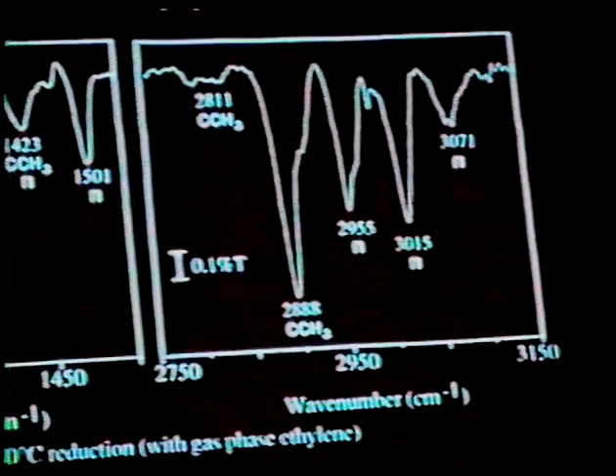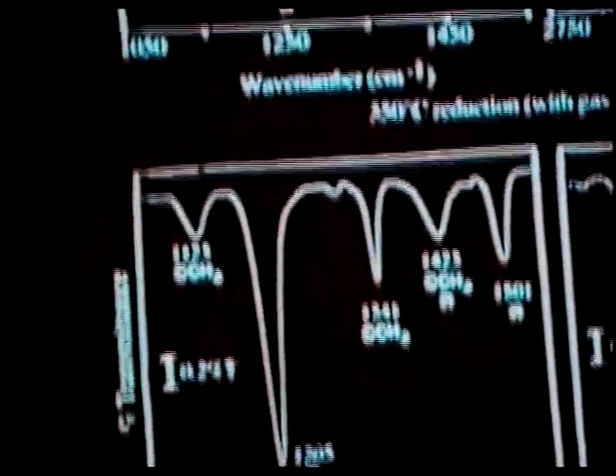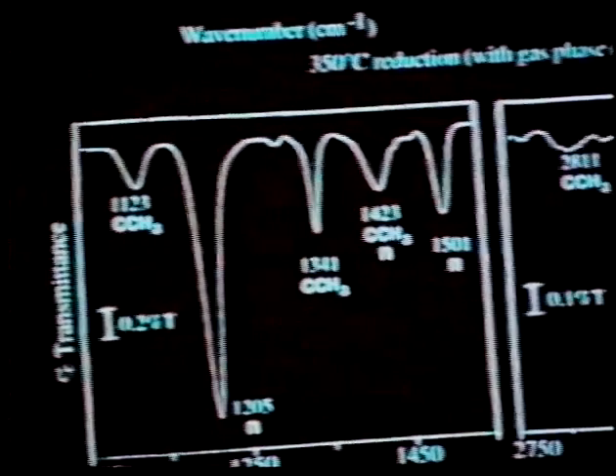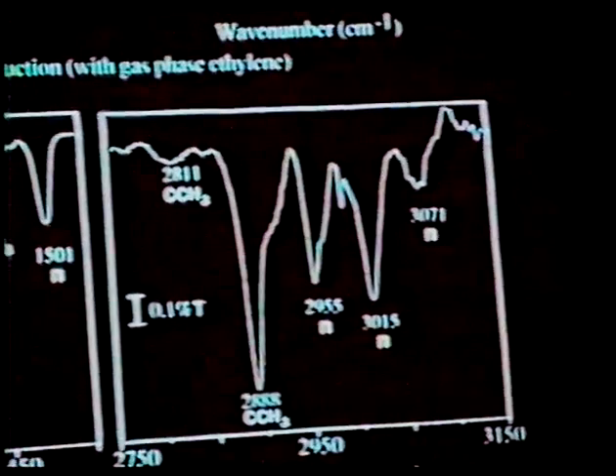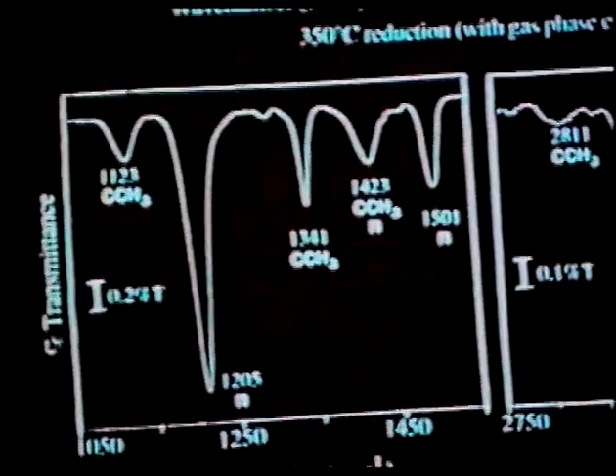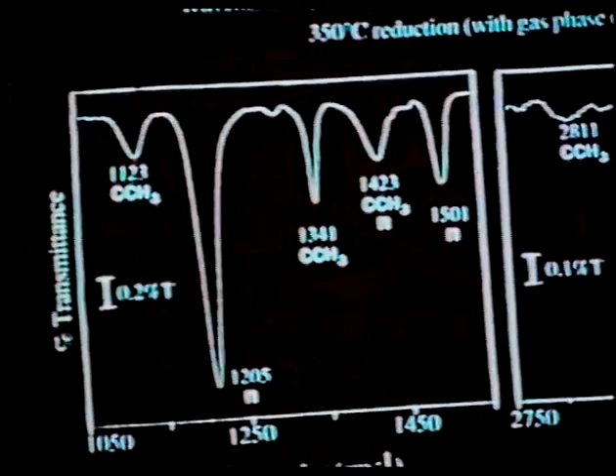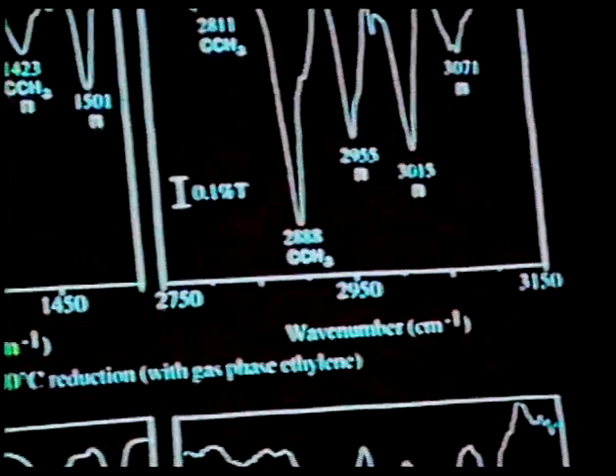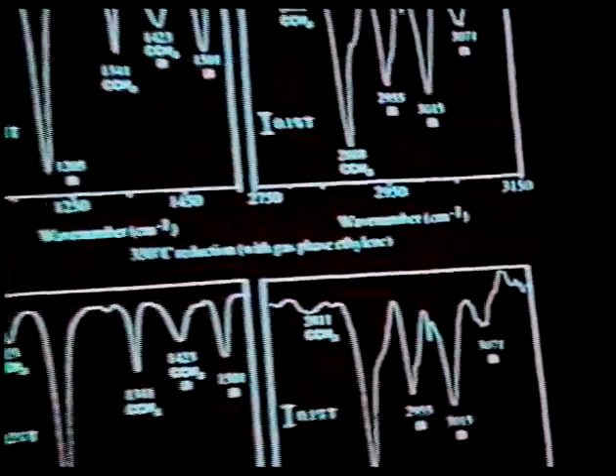Now, the reason I show this is to show you that these two spectra at this point are essentially identical. You can lay them on top of one another, and there is really very minor differences between the two. It clearly demonstrates that all of the sites responsible for forming the pi bonded species are there. Equivalently, the numbers of ethylene that you form at this point are virtually identical. You would say that the particles, for all intents and purposes, are exactly the same.